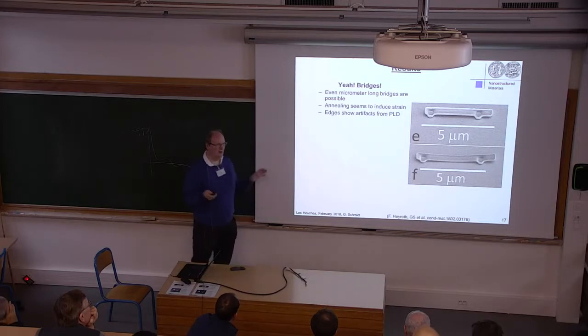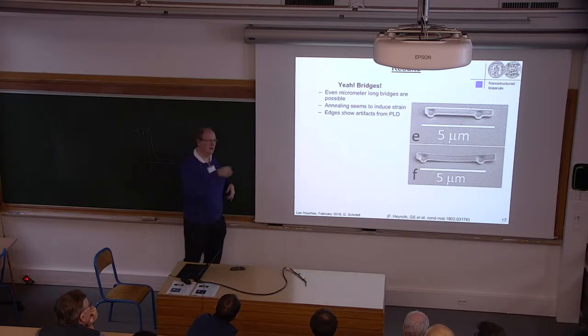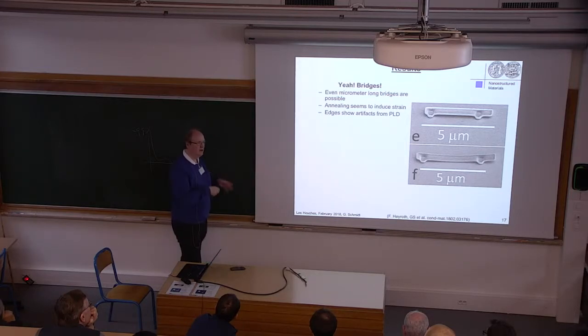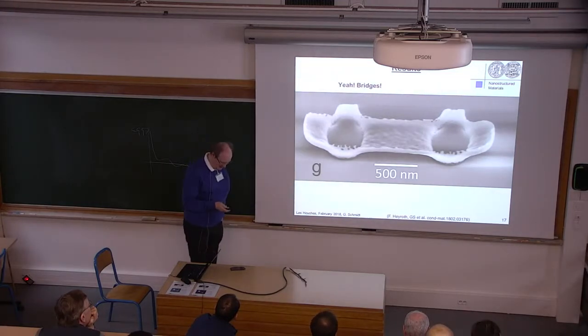But we know that the properties of each PLD system are completely different. For example, I've talked to other groups, for example the Paris group. They have tried to do the same thing, and they don't get the nice quality after the annealing. Here we annealed in oxygen. We can also anneal in argon. It's the same thing. The important thing seems to be that you deposit in oxygen. If you deposit in argon, then you can anneal however you like, you don't get nice material. However, if you anneal in any gas afterwards, after growing in oxygen, you get the good material. Anyway, this is just how the things look from the outside.